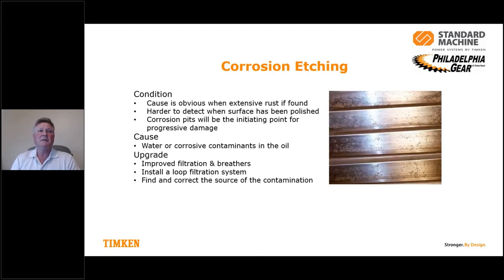Corrosion etching. It's really obvious if you can see some rust on the gear, you've got some corrosion. It's really hard to detect if somebody comes along and polishes it off with an emery cloth, and then you don't get to see what was sitting on the surface of the gear tooth. We always recommend not to polish or change the condition of the gear before it's sent in for inspection. Corrosion pits will be the initiating point for progressive damage. You can see by the picture what it looks like. It definitely looks like an etching condition.